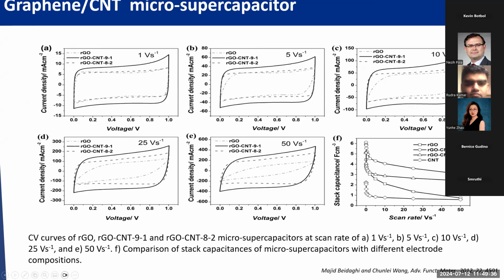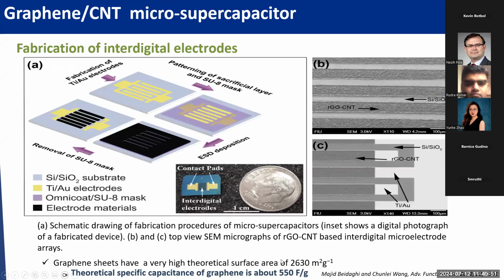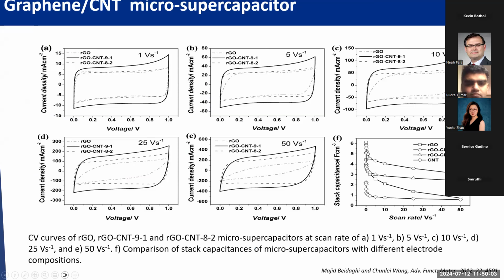But once you add RGO with CNT, what happens is, if you have pure RGO, those RGO will restack. So you basically lose the surface area. Even though theoretically the surface area of graphene is very high, 2,630 meters squared per gram, in reality those reduced graphene oxide sheets will restack together. So you don't really have the 2D material advantage.